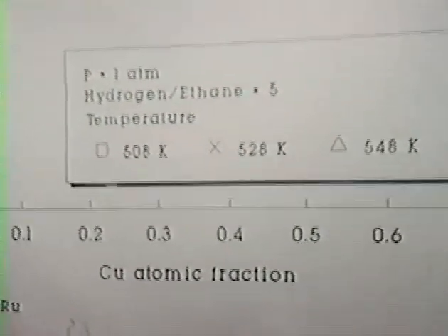We plotted the rate in terms of moles of methane produced per second per total moles of ruthenium in the catalyst as a function of copper content. At low temperatures, we start with fairly high activity for pure ruthenium on silica, but as we add copper, activity drops considerably — by about the time we reach 20% total metal being copper, activity is over an order of magnitude lower than the pure catalyst. At higher temperature, we extend measurements to higher copper compositions to obtain a good set of reaction rate data.